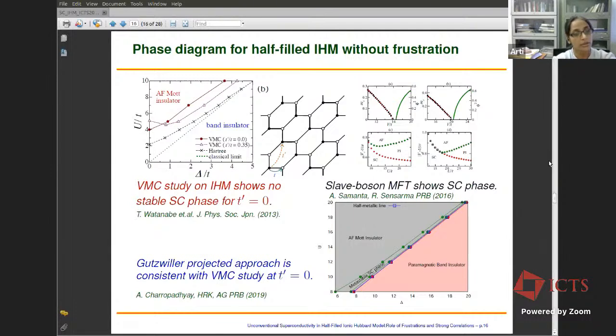There were also studies using slave boson mean field theory, which surprisingly showed a stable, broad superconducting phase even at half filling in the large delta limit of the Ionic Hubbard model. So this is the only case which is not consistent with our phase diagram in the absence of next neighbor hopping.